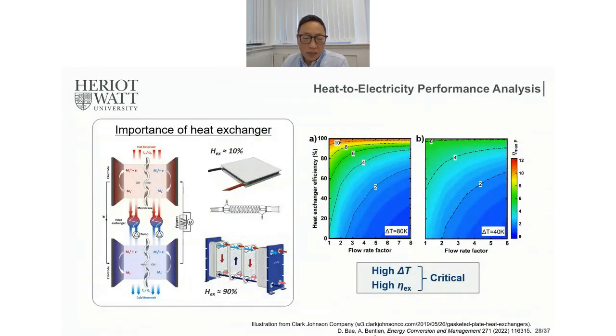Let's move to the heat exchanger. The importance of the heat exchanger is highlighted on the right side. You can see here that at the high temperature gradient condition, no matter what the flow rate is, if the heat exchanger efficiency is high, then we can have 10 to 12%. But if we have a poor heat exchanger efficiency, as you can see here, depending on the flow rate factor, there is a huge drop in the conversion efficiency. These figures highlight that it is important to have a high temperature gradient and at the same time a good heat exchanger efficiency.